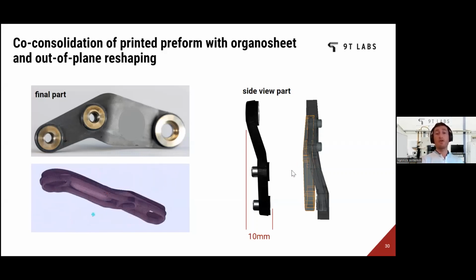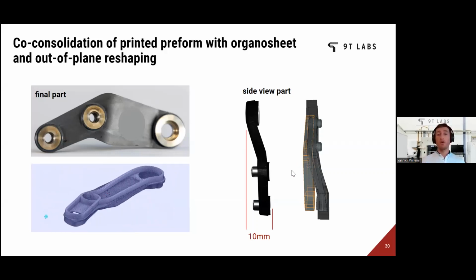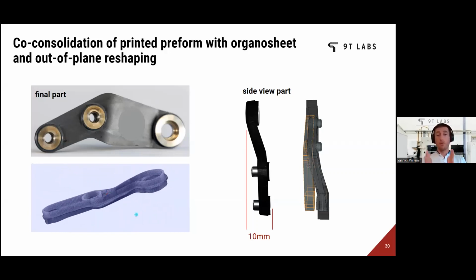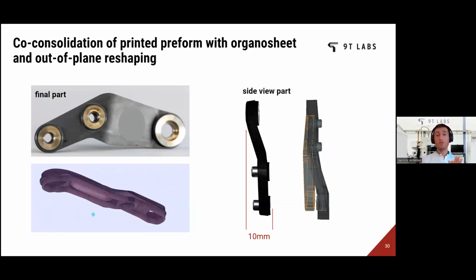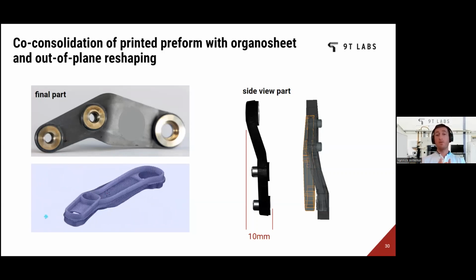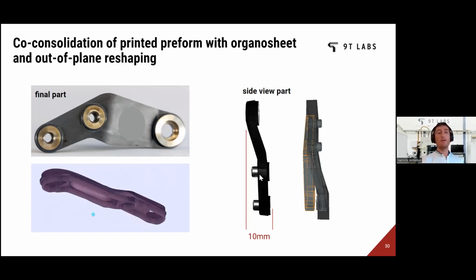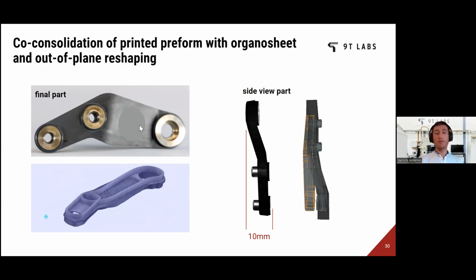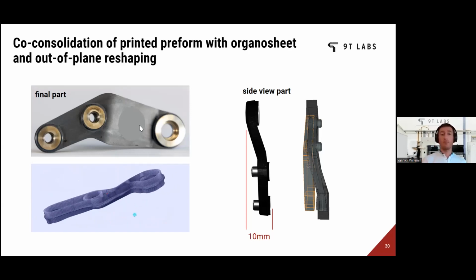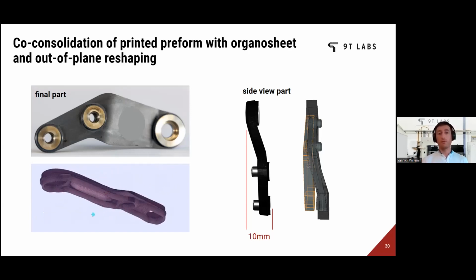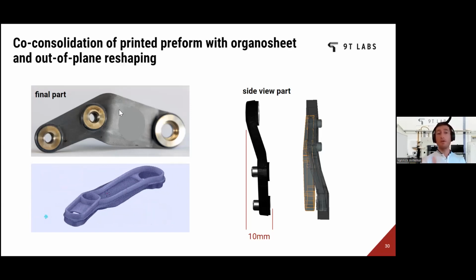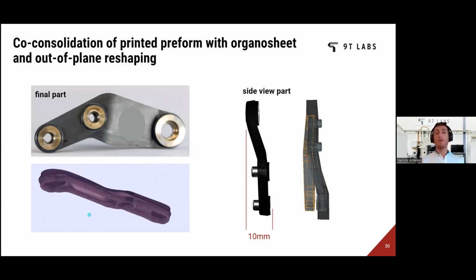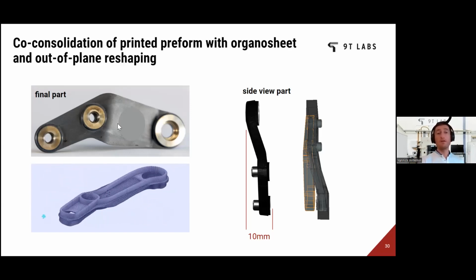It's quite some reshaping, while obviously co-consolidating both all our printed layups with the organosheets, and also co-consolidating or integrating those metallic inserts, so that the part, as shown on the top left, is really coming out of the post-process, of the molding process, like shown here. So very good surface finish. We might need some tumbling for the edges, but no milling, nothing on this part. So we are ready to go.